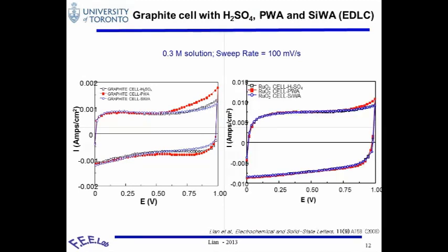We further look into a different type of material. In supercapacitors, there are two kinds of energy storage mechanisms: double layer versus pseudocapacitance. For pseudocapacitance, the gold standard is ruthenium dioxide, so we look at that. Again, we see a very nicely shaped square that tells us the material and solution is safe, the electrolyte is okay to use.